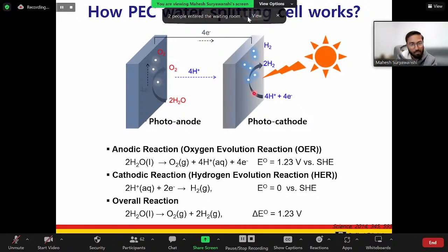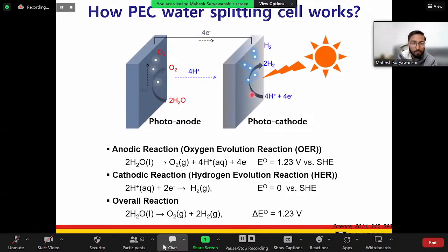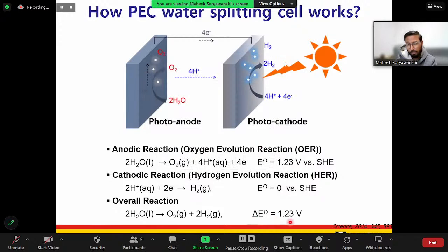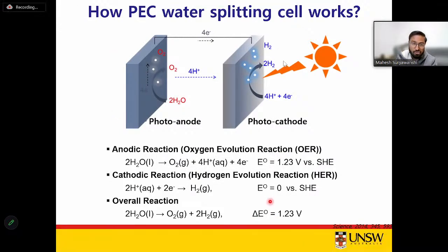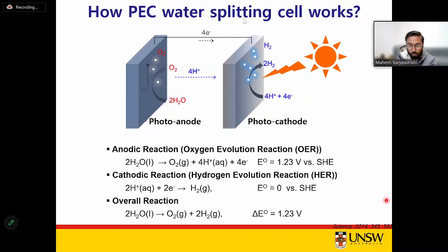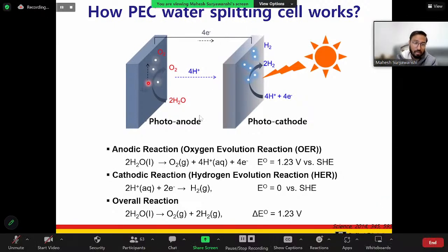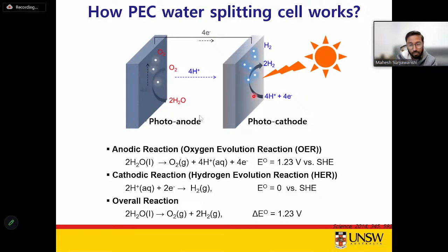So when I say thermodynamically favorable, we need to look at their energy band alignments, which should match with the particular potentials on the energy scale bar. If that matches quite well, then charge injection happens into the water splitting reaction. When this reaction is thermodynamically favorable, the reduction of water to hydrogen and oxidation of the reduced redox mediators occur on these photoelectrodes: at the photoanode, which is the oxidation reaction, and at the photocathode, which is the hydrogen evolution reaction.